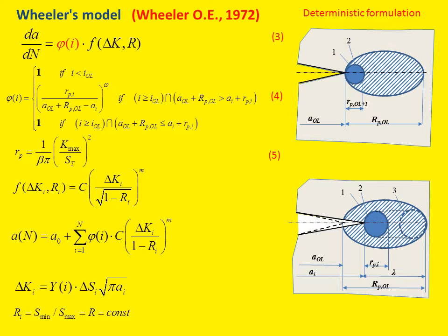His model is based on the assumption that crack retardation is caused by the large monotonic plastic zone ahead of the crack tip that is induced by the overload. So Wheeler modified the Paris equation by introducing a retardation function phi that is defined by equation 4. The key parameters of the model are the shape exponent omega, the size of the plastic zone induced by the regular loading cycle RPI, and the size of the plastic zone induced by the overload cycle RPOL.